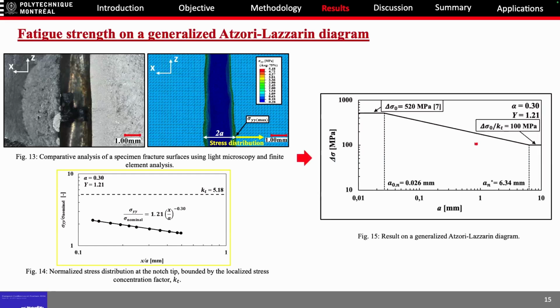The red dot represents the fatigue strength from our experiment. The black line represents the prediction from the notch theory. And then I superimposed the LEFM, which seems to predict the fatigue experiment well. But this is one of the specimens. Now I'm going to show you every specimen.